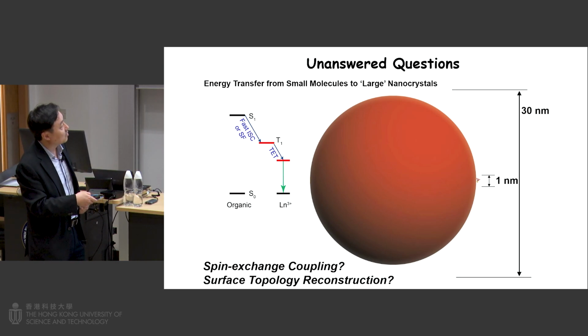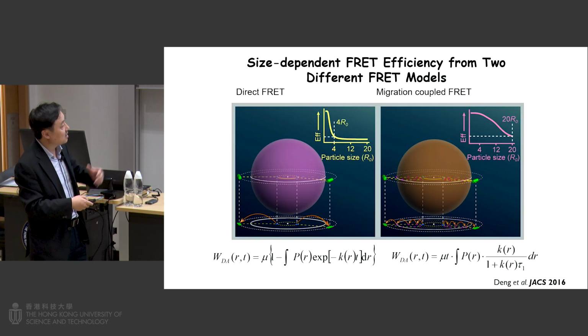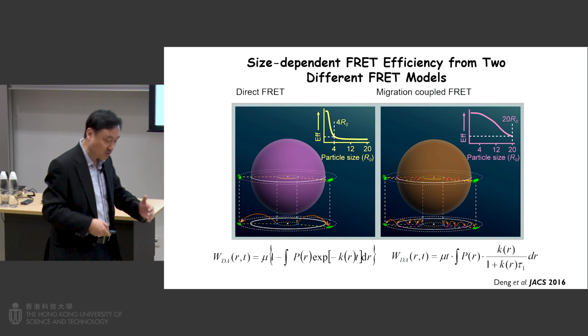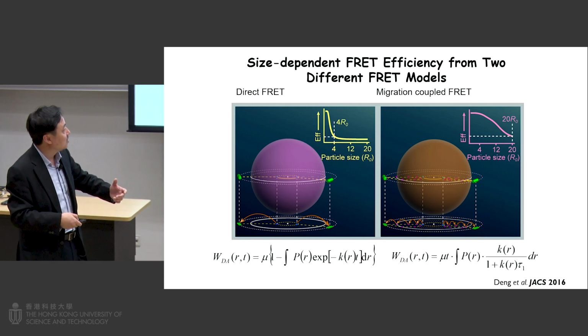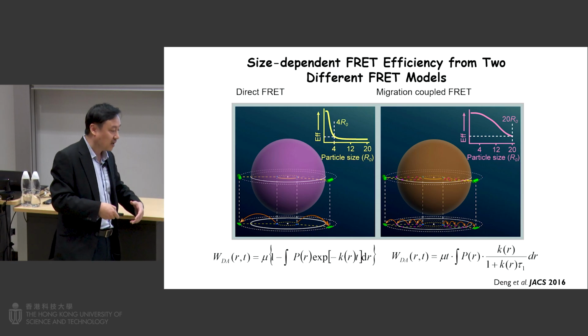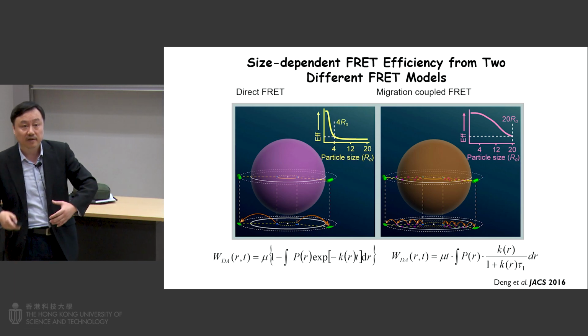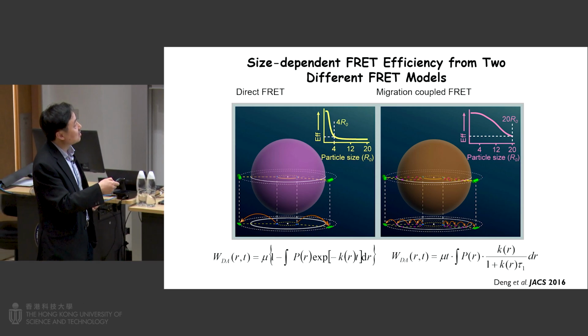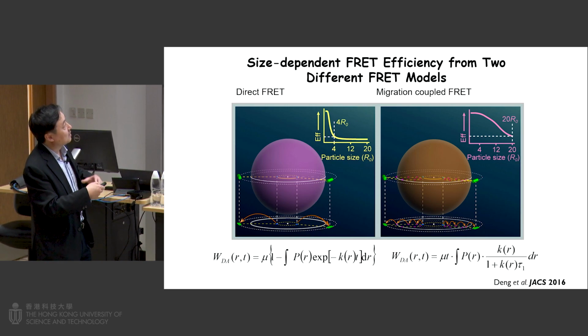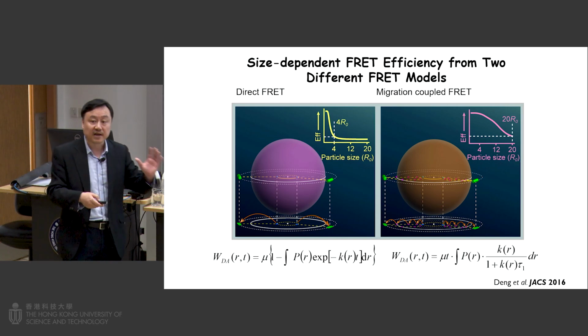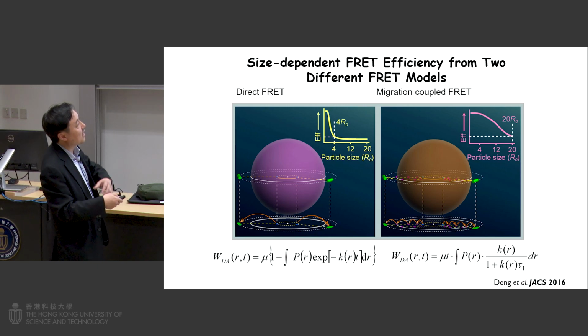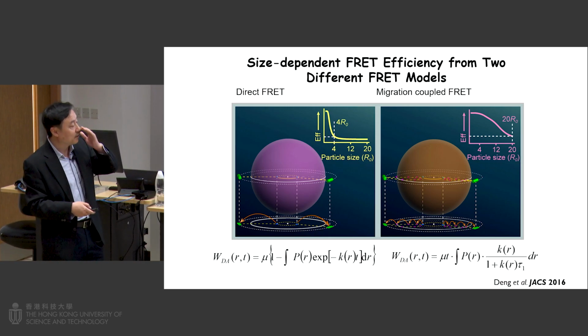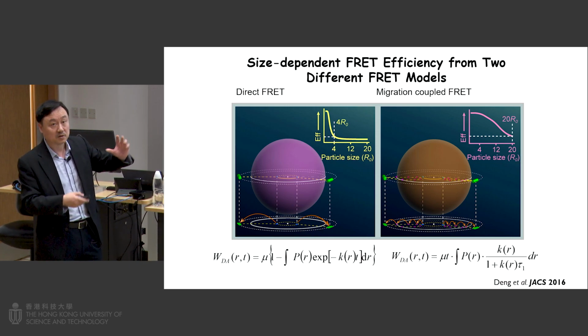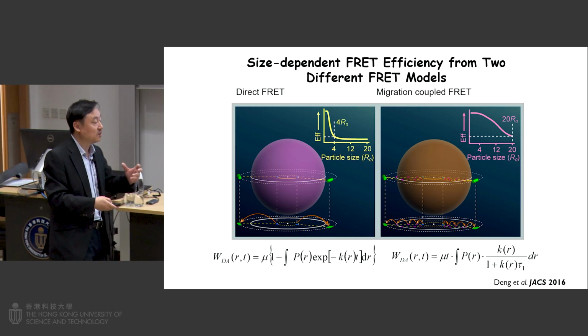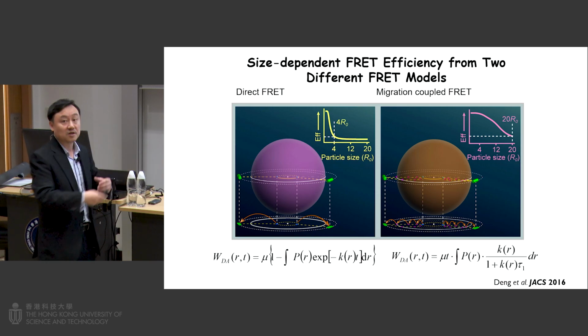So you can take advantage of lanthanide ions, as I mentioned, energy migration shown here. We show that using energy hopping, energy migration is more like energy hopping through the Gd lattice, and then transfer to emitters. So if 10 nanometers is too short and 20 nanometers is too far for FRET, I can use lanthanide ions as intermediate migrators. We are showing this in simulations. Without energy migration, the critical energy transfer distance for FRET is basically 4 or 5 nanometers. But using our designs, you can see we can extend it to almost 20 nanometers. We validated this hypothesis using experimental data. We used the core-shell structure to control the migration distance.